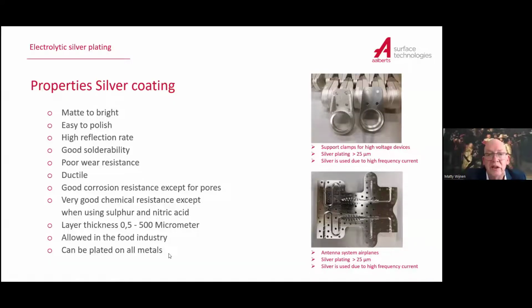Okay, good. Good corrosion, good chemical resistance. The only thing which is affecting silver is sulfur. And everyone says, okay, silver is a nice layer, but it gets black. Yeah, that's due to the sulfur, which is in the air, the SO2 in our atmosphere, and will turn silver during time into a black coating.